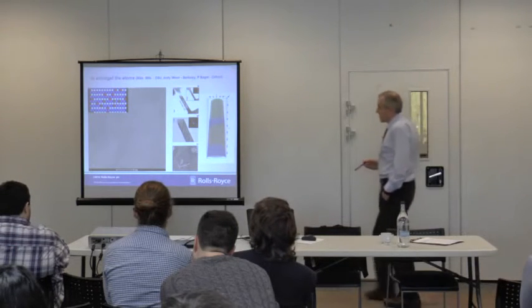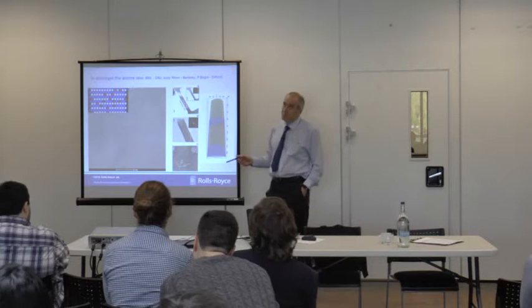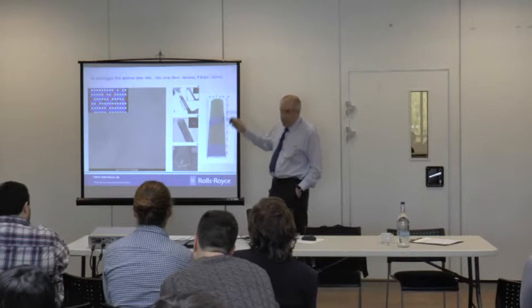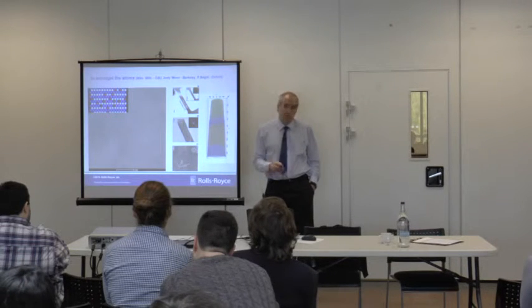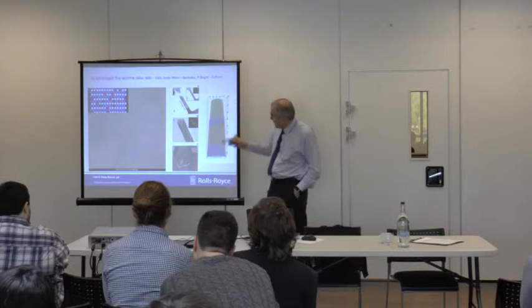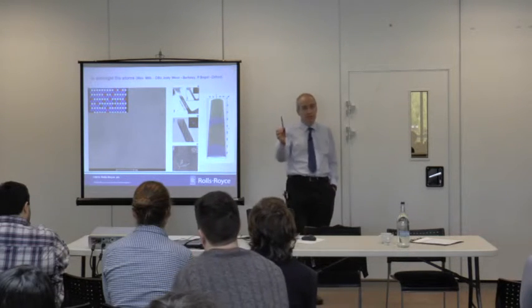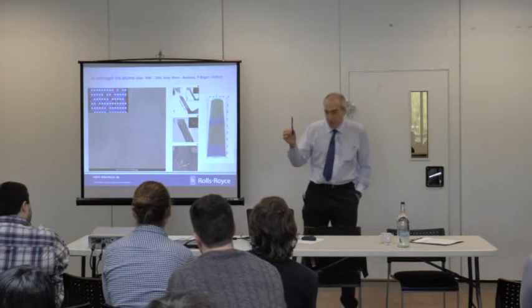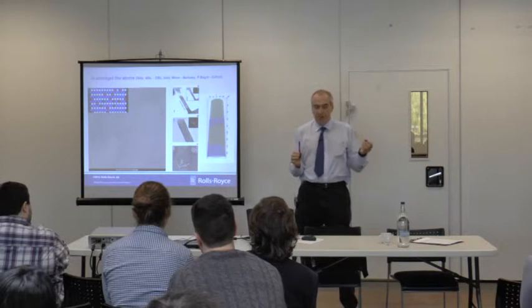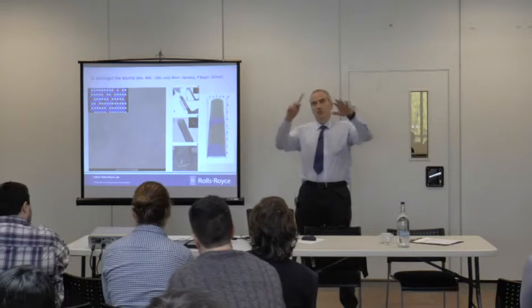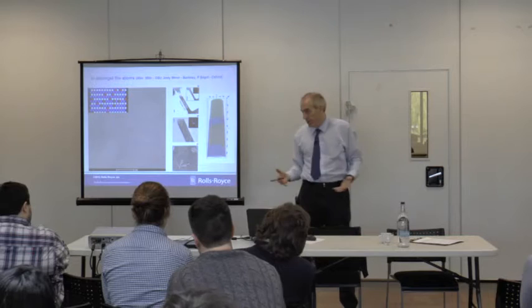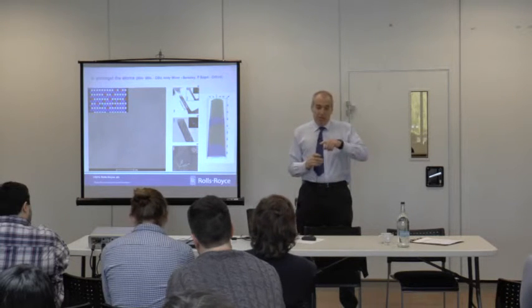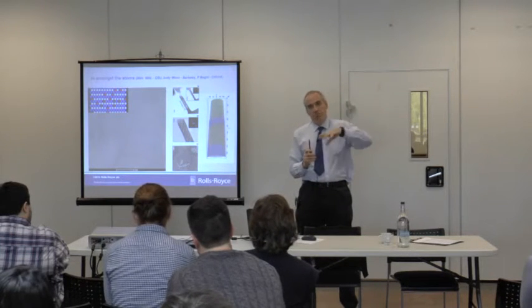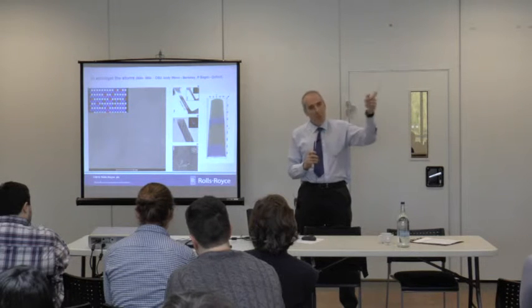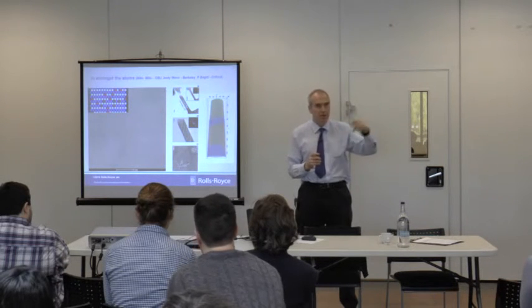Another technique we use, where the UK are pretty much world leaders, which we've used in anger for service problems, and we published that as well, is a thing called atom probe tomography, where you take a needle of material, you apply a big electric field to it, and then you pulse it either electrically or with a laser fairly quickly. You've got a grid around the inside of the machine, electrical grid, so you know where the ions that come off hit, and because you've pulsed it, you know the charge, you know the time for it to hit, so you know the charge to mass ratio.